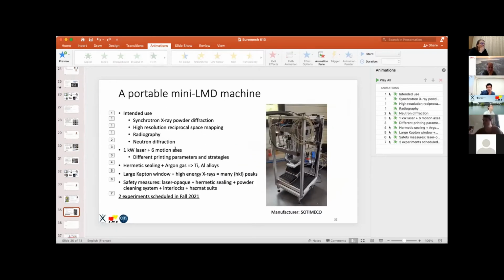What I said is that we can do it in both transmission and reflection mode. And the reason why I say that is, instead of Kapton, we can remove the Kapton and use aluminum walls. If we use thin aluminum walls, then it's practically invisible to the neutrons. Then you can set it up in such a way that you print at 45 degrees and you can study intermittent start and stop diffraction measurements, so while building in either mode. And then of course you can do a residual stress measurement for the whole thing at the end of the build. But here you can focus on a region or on a layer and study how the stresses evolve as you continue building. So that's one of the ideas.